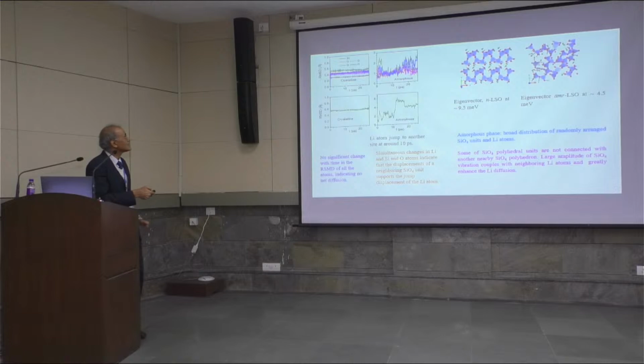Okay, then if I just pick up one atom and see how its root mean square displacement is changing with temperature, then in crystalline material it is a constant. Here, this is the displacement from the original position. So you can see that it shows some variation, then it shows a jump. So this is like jump dynamics. Whereas in amorphous material it is more a mix of jumps as well as a liquid-like continuous process. So this is the microscopic understanding.